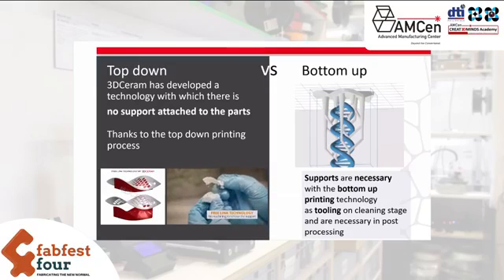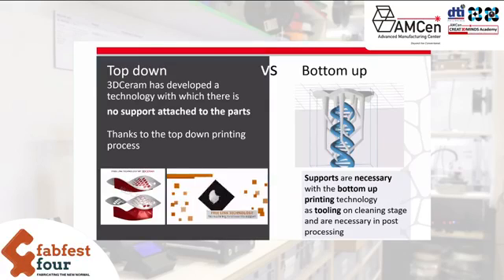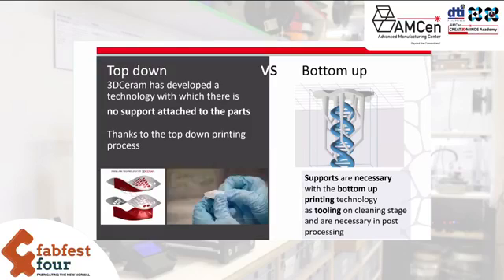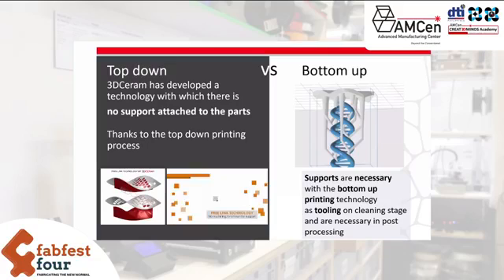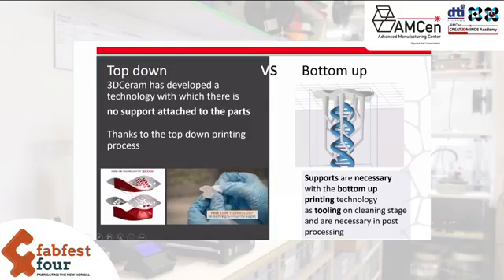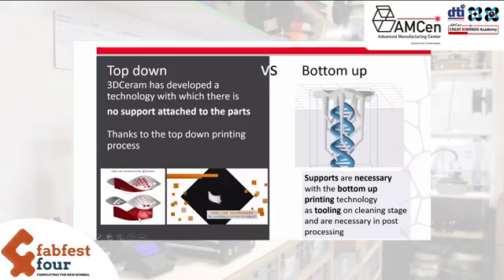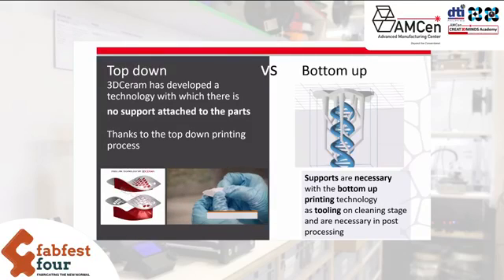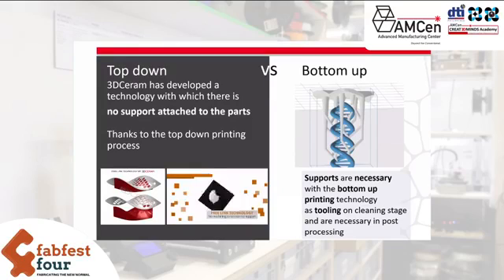And thanks to the top-down process and the viscosity of the slurry, we do not need any links between the part and the support, as you can see on the picture and on the video. For example, if we want to print the white part, we design the support in red, and during the printing run, we have a very small gap of uncured slurry between the part and the support. So we don't have any link, any pillars.